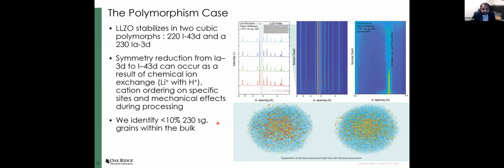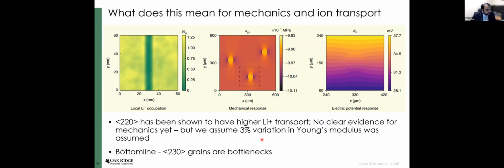And so what is the implication of these space groups, right? So the question is, if we have a space group that is distinct from the bulk, what does it entail? So we took help from our modeling experts over at Purdue University, Partha Mukherjee and team, and we did some simulations at multiple length scales to understand the impact of having a domain that is essentially less conductive or with a slightly different mechanical property embedded within the matrix of a bulk material.